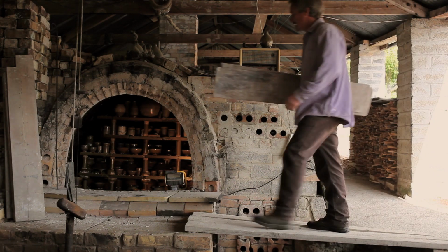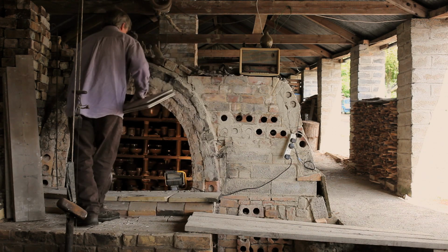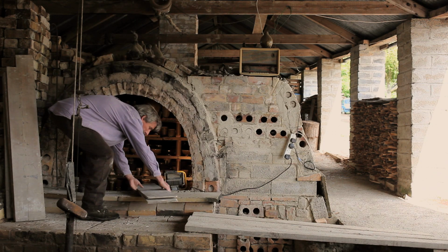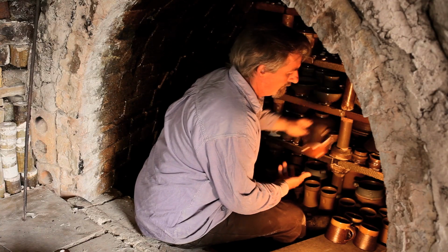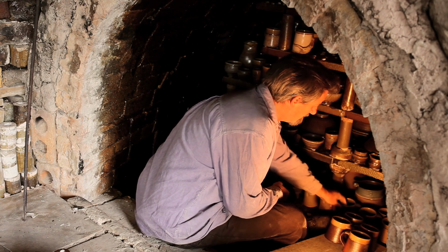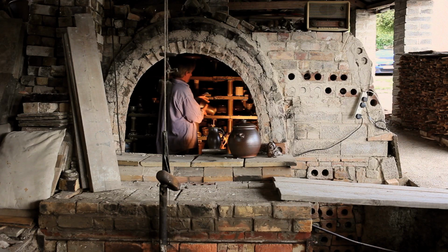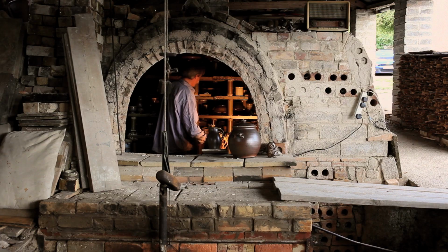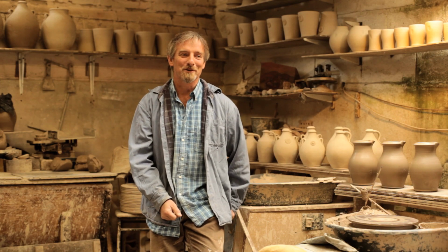Still, after 3 days, it will be 200 or 300 degrees in the chamber, and we just crack the door, let the last of the heat out, and then perhaps the next day we can get the pots out and see what we've got. It's genuinely a slow process, slow pots.